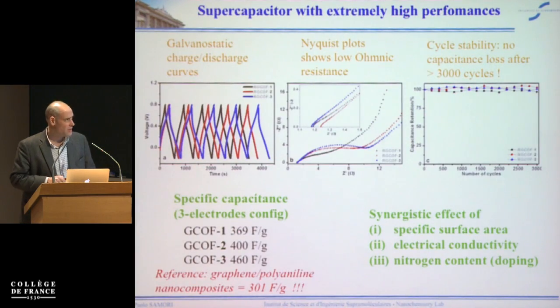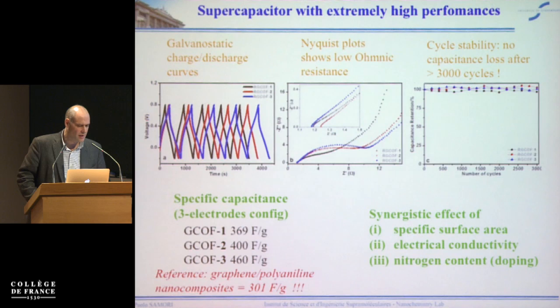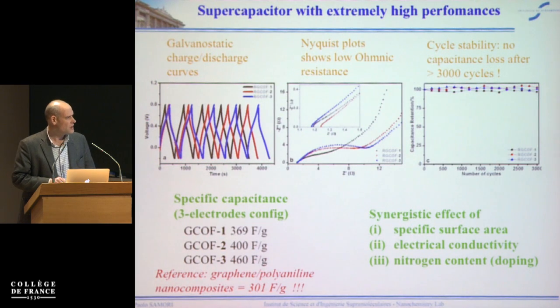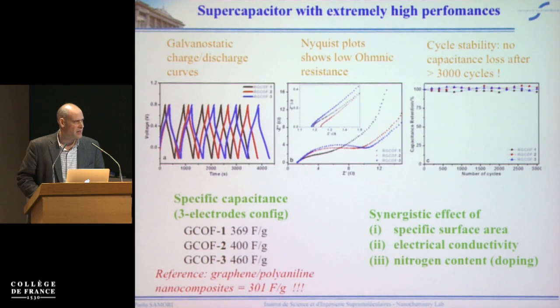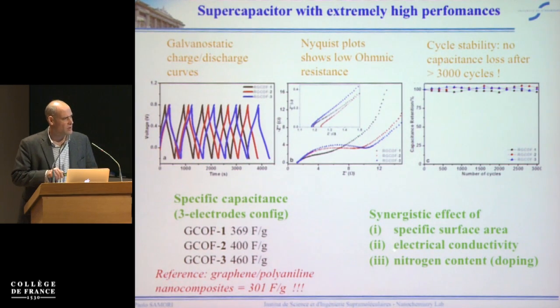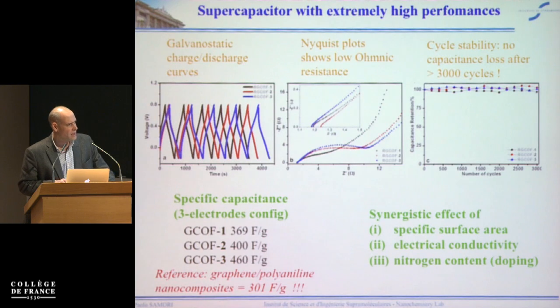Nevertheless, we have been trying to test this kind of architecture as an electrode for supercapacitors. Here, of course, we take advantage of the specific surface area, and we do a bit of hydrogen reduction in order to gain some electrical conductivity. Otherwise, our system would be completely insulating. And the use of benzidine allowed us to have a certain amount of nitrogen doping in our system. The results were quite positive, in the sense that we can get a specific capacitance that is, in all three cases, higher than that of a standard graphene-polyaniline nanocomposite.